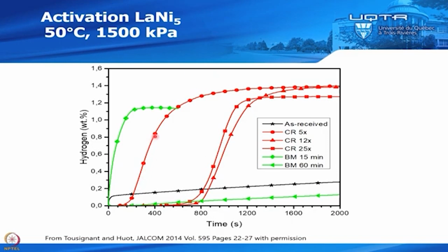It's quite fast, not as fast as ball milling, but you see we have almost full capacity. And if we roll 12 times or 25 times, you see that 12 times actually it's getting a little bit slower. The incubation time is longer, but we have almost no loss of capacity. But if we keep cold rolling, we have a loss of capacity because again we do all of that in air. So as we roll, we will start to produce oxide, and then it will reduce the capacity.